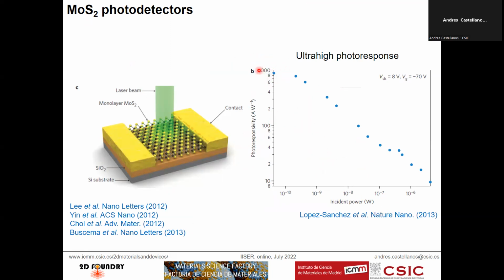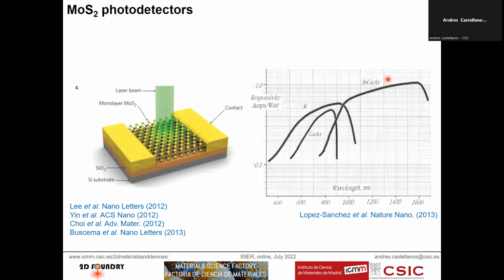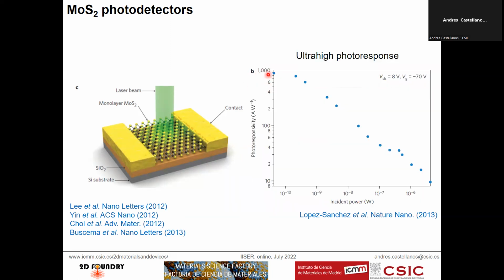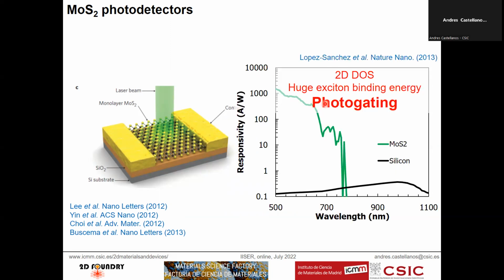Okay, so remember that we already discussed that in silicon, indium gallium arsenide, we are, let's say, about 1 amp per watt or less. And in this case here, we reach up to 1000 amps. So this motivated the community a lot to start studying these two-dimensional materials for photodetectors. But as I have to stress, up to now, most of the research groups still work on molybdenum disulfide or cousins of molybdenum disulfide, transition metal dichalcogenides, basically.